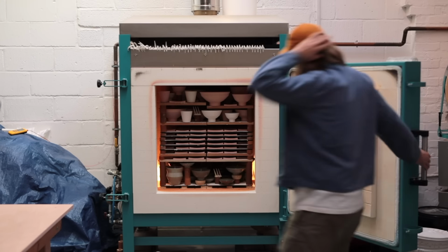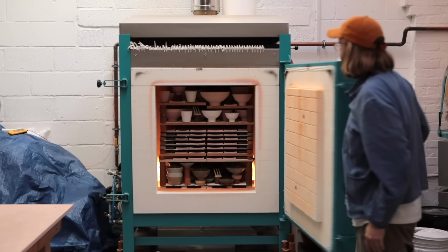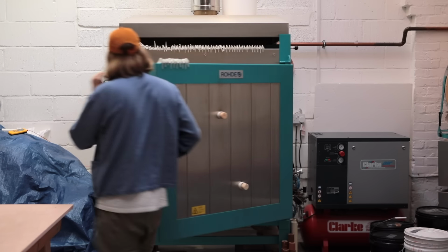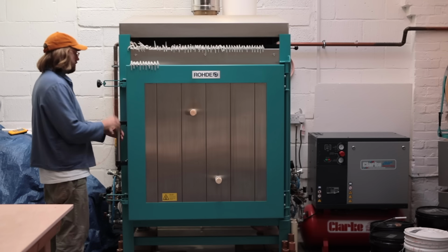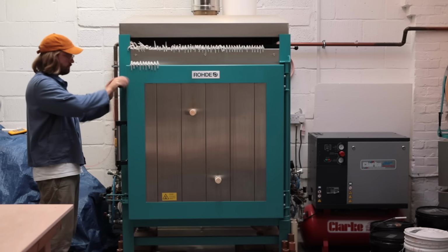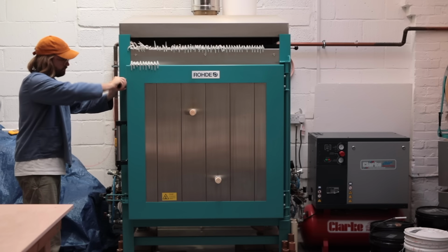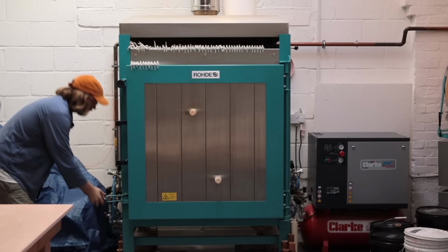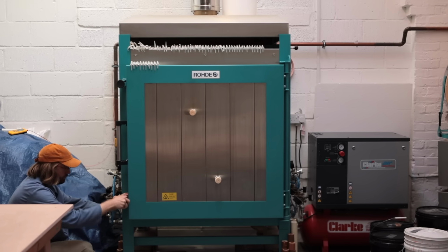And with all 4 burners lit, the door can be swung closed and fastened tight. From beginning to end, this entire process takes about 9 hours, and initially the temperature is increased really gradually, as if you fire too quickly, there is a chance that you can blow up the pots inside. You'll hear a few muffled pops, and then a scattering of fragments. It hasn't happened to me in a long time, since college, in fact.